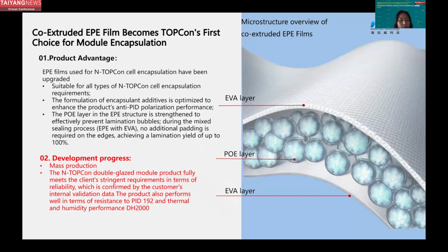Regarding the TOPCon part, in fact, we know that it is in the process of ramping up volume. It is really a very rapid evolution of the demand. At present, according to our statistics, EPE products have become a preferred material for TOPCon. For this EPE film, first we need to upgrade the formula to ensure the reliability. Second, we have improved the formula to enhance the cohesive strength of the POE layer, so that it can have 100% yield when laminating and sealing, especially for EPE with EVA without the four corners of the frame. At the same time, this EPE product has been fully certified in terms of client reliability.